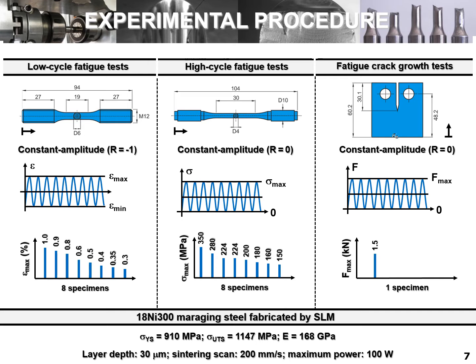The material utilized in this research is a maraging steel fabricated by selective laser melting. The main mechanical properties as well as the main processing parameters are exhibited at the bottom of the slide. In order to test the model, some experimental work is needed. We have conducted low cycle fatigue tests under fully reversed conditions for strain amplitudes between 1.0 and 0.3%.